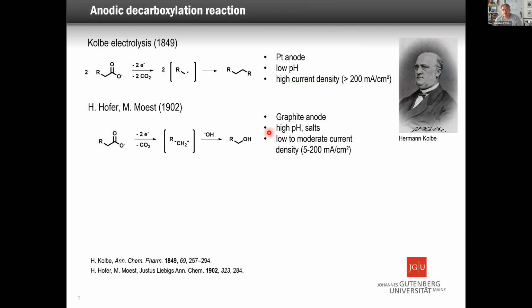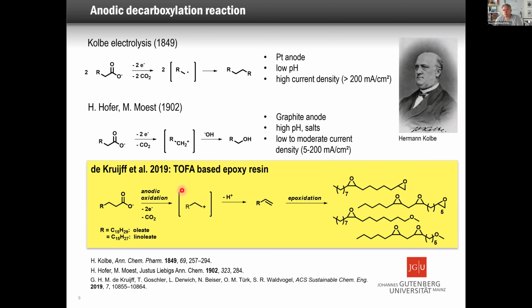This is the typical way which is done, but besides the Kolbe, which was more than 170 years ago, Hofer and Moest found a way: if you do it in this way, especially with a substitution pattern here, then you generate more or less a cationic species which is trapped by alcohols or water itself. This is a way to functionalize molecules. In most cases, you can make double bonds if there's no water or no methanol as a base there. I will briefly show you that we use that to lower the oxygen content, in that we make double bonds in there. They usually already have double bonds in a long chain, but then we have more double bonds in there.